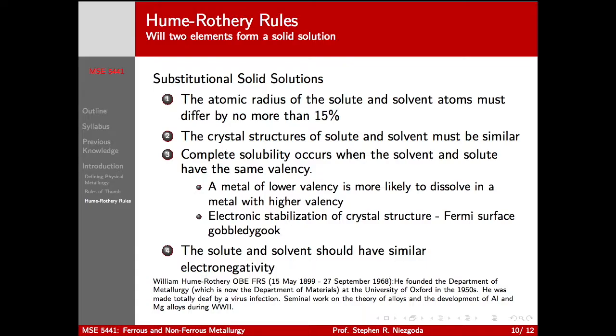So why is it that the solute and the solvent, or the matrix and the alloying elements, the primary metal and the alloying elements, should have similar electronegativity? What would happen if they had very different electronegativity? Intermetallic secondary phase. So high electronegativity difference for bonding gives you what kind of bonds? Ionic bonds. So intermetallics with a high ionic character are going to tend to be very, very brittle.